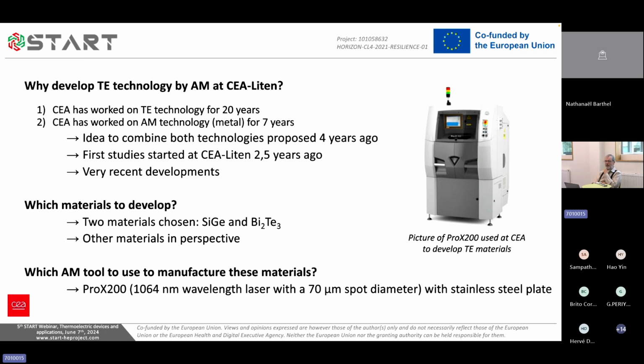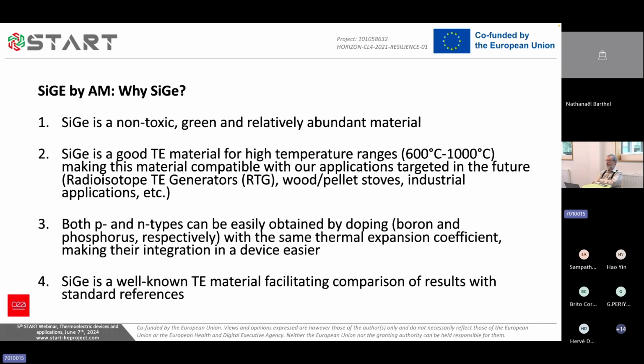We have investigated silicon germanium and bismuth telluride, as I explained, and we have other materials in mind. It's possible, but this is a long shot. So this ProX machine works with an infrared laser, 70 micrometer spot diameter. And we work currently on a stainless steel plate, but more developments are possible. So why silicon germanium?